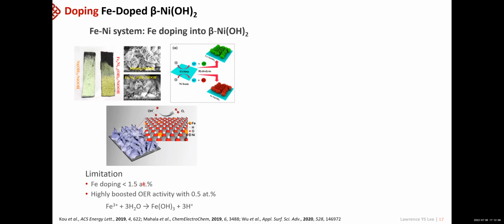And yet the best OER activity came when they had only 0.5 atomic percent. I believe this is not because this is really the optimal condition, but because when they tried to dope more iron species, this high concentration of iron actually produced a lot of protons, making the reaction condition very acidic. That destabilized the grown nickel hydroxide species, which easily detached from the surface. So when you really want to do the OER, that is very poor because they even come off the surface.